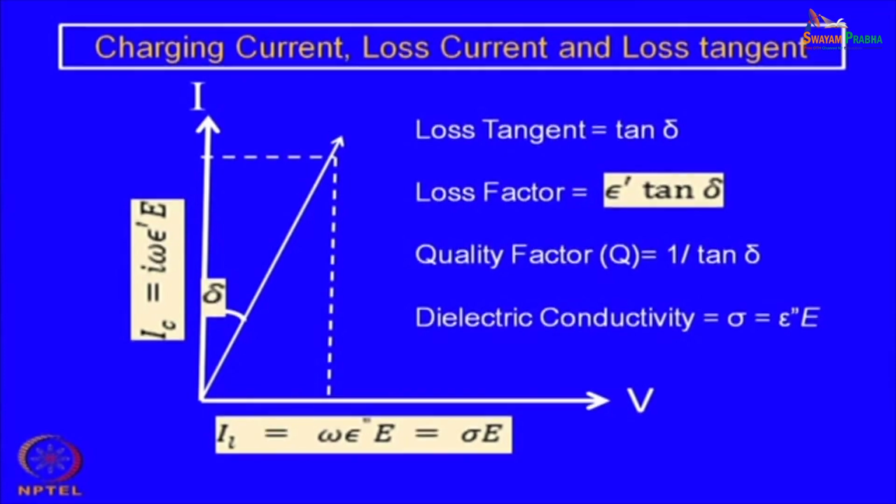So, the capacitance value also includes a geometric factor, but the dielectric constant as well as loss tangent or dielectric loss are material parameters and intrinsic properties of the material, the way we prepare it, the way we synthesize it, or the particular crystal structure, the chemical composition, and so on and so forth.